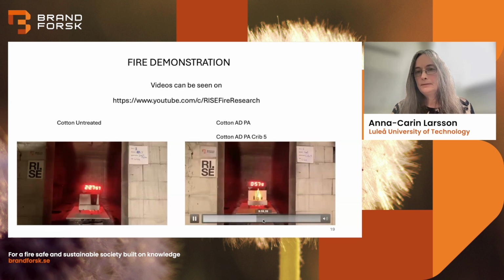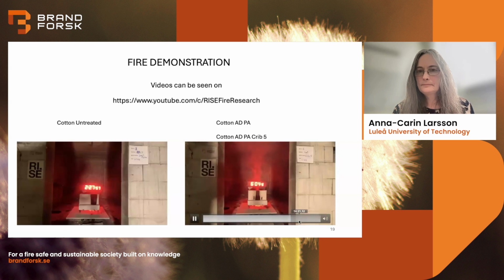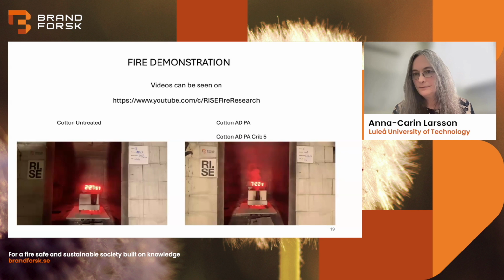We can jump ahead a bit here. After 4 minutes, the crib itself has burnt completely, and we can see that there is some charring on the cotton. It expands very, very slowly.